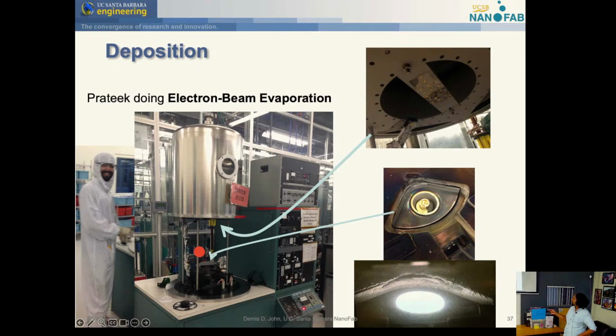So at the bottom here, in this little area, we have, in this case, literally a little pot of gold pellets, ultra high purity gold pellets. And then your wafer goes up on the top, facing down. So it's facing towards the gold, where the gold's going to come out. Okay? Put down the bell jar, hit start, it pumps all the air out. You have to wait 30 minutes for enough air to get out. And then you heat up, in this case, the gold crucible.